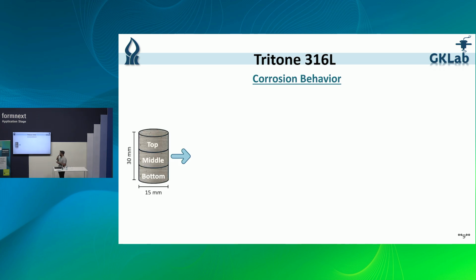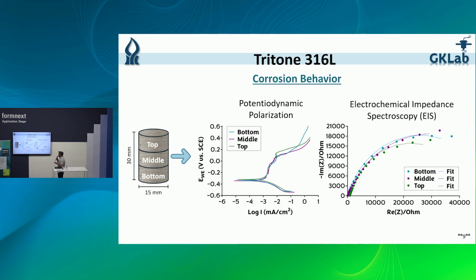As part of the corrosion behavior evaluation, I divided the sample into 3 areas and examined whether there is consistency between the different areas in terms of corrosion resistance. The tests were conducted in a solution that simulated the physiological environment, PBS. Here we can see the corrosion resistance in terms of potentiodynamic polarization and electrochemical impedance spectroscopy curves. The obtained curves in each plot demonstrate high corrosion resistance and that there are no significant differences between the examined areas.